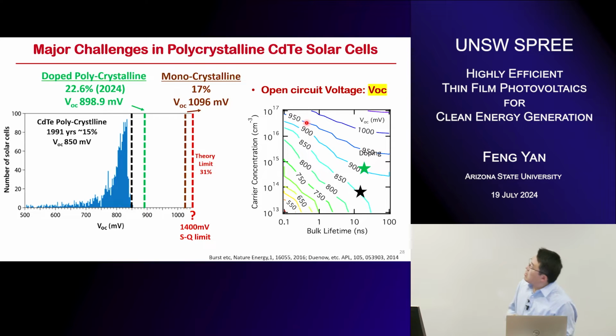We demonstrated around 1.1 volt. It's promising that a high open circuit voltage is achievable. So what drives us is how we close this gap between the polycrystalline and the single crystal, right? And if we can achieve around 1 volt, then we have the correct pathway to further improve the efficiency.